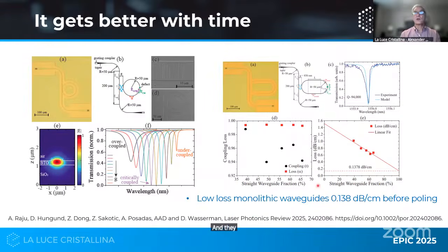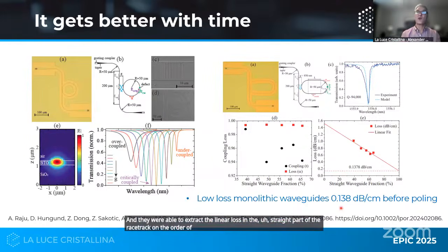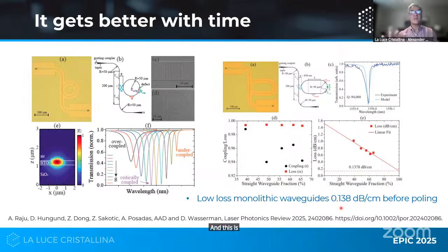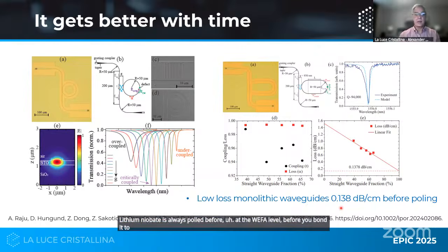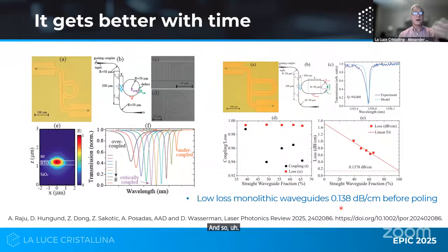And they were able to extract the linear loss in the straight part of the racetrack on the order of 0.14 decibel per centimeter. And this is really fantastic, and that's before poling. So none of this barium titanate is poled. Lithium niobate is always poled before, at the wafer level, before you bond it to a substrate. And so there is rapid progress. We're not the only people who work on that.